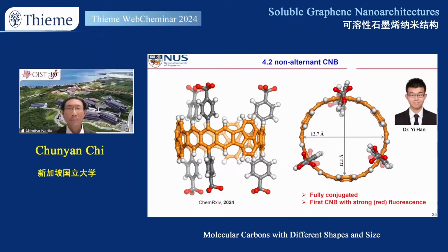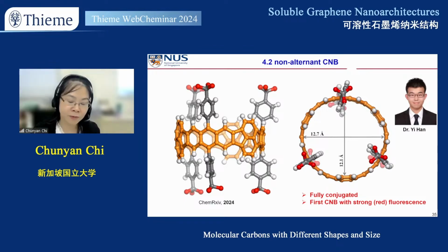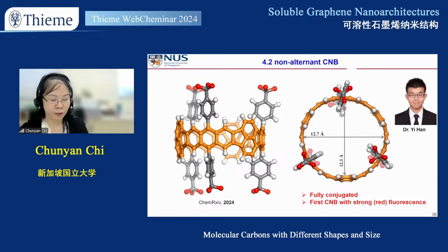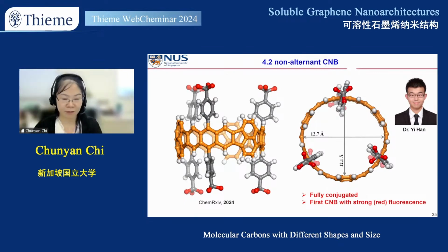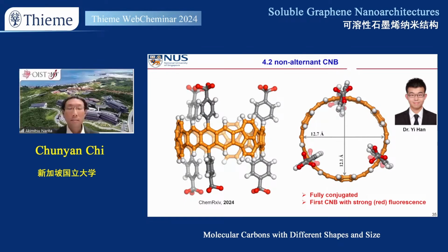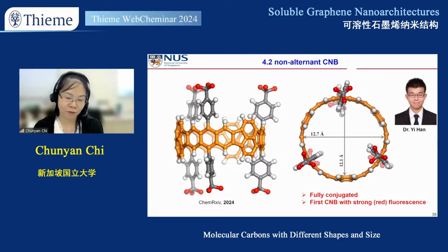Have you observed both NMR and EPR at the same temperature from the same sample? Yes. For most of the diradicals we study VT-NMR and VT-EPR, and they are very consistent. For example, if a molecule has a small diradical character, then at room temperature the peak is just slightly broadened and the ESR intensity is weak.